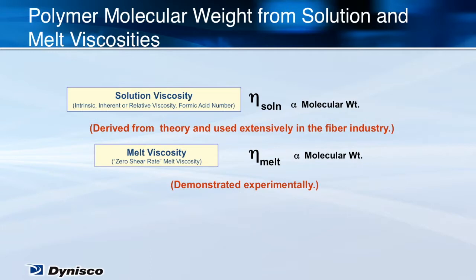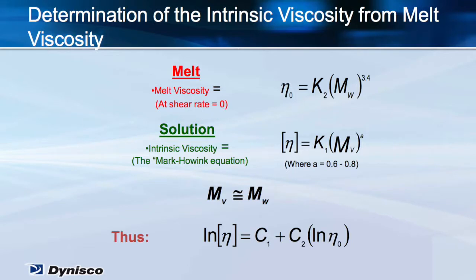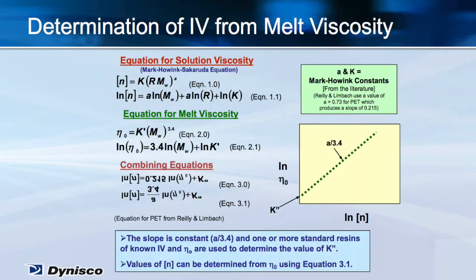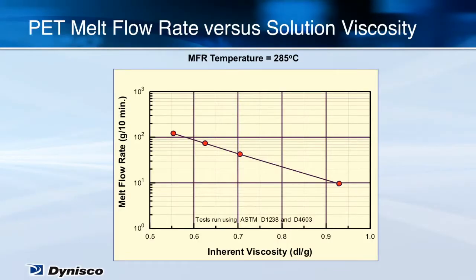The idea of this correlation is that both the zero shear rate melt viscosity and solution viscosity have been shown to be correlated to the molecular weight of the polymer. There is mathematics behind each of the correlations. The idea is that the equations are both related to the molecular weight, so they're related to each other. Dynisco found the solutions to these equations, and Jim Riley, a former Dynisco employee, published a paper on this topic that we still distribute today. It is referenced on the slide and has all the details of his work. We have implemented this equation on our machines so they will report the IV of PET based on the melt flow rate at 285 C.